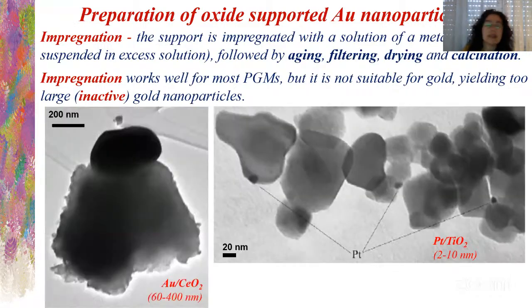Impregnation is good for platinum group metals like platinum, palladium, and so on, but it's not suitable for gold because it gives too large, inactive gold nanoparticles. We have here an example: gold on cerium oxide. This is gold, the darker one. The nanoparticles are huge, 60 nanometers.